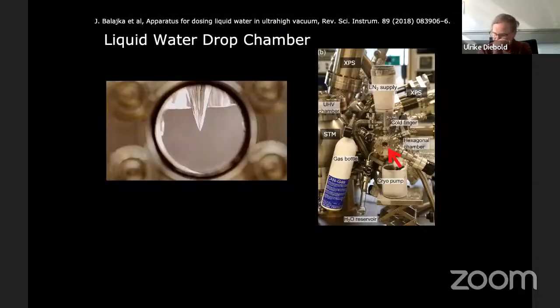So what Jan and other people in my group came up with was that we dose water in a little special setup. Here, this is an ultra high vacuum chamber. This is our scanning tunneling microscope. This is our X-ray photoelectron spectrometer. There's a little side chamber, an ultra high vacuum chamber, connected to the main chamber. If you look through this window, you see a little tip. This is the tip of a cryostat. Everything is in ultra high vacuum. We can move the sample in and out without ever exposing it to air.